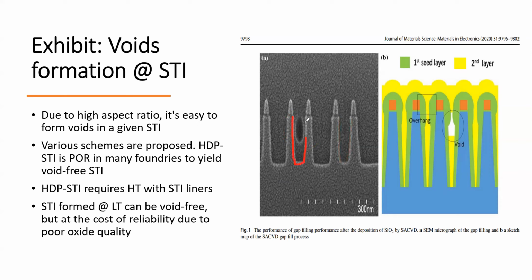This aspect ratio obviously is higher than this one, right? Because this is wider and this is narrower, right? Aspect ratio is the height divided by the width of the hole, by the diameter of the hole. And this one is higher, and you can see that there's a big void here. There's tons of trouble. Imagine if you CMP here, then the hole opens, and all the dirty things come in. Or even with the dirty things coming in, the oxide here is weak. Then you might have reliability issues. So this is the problem.